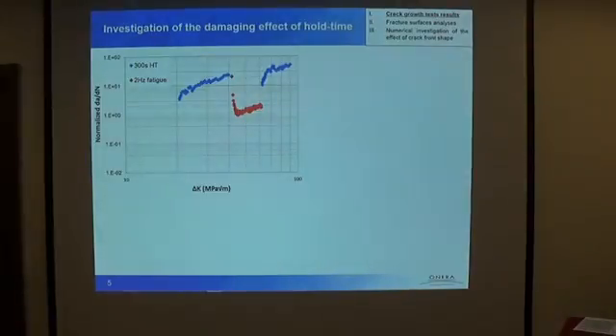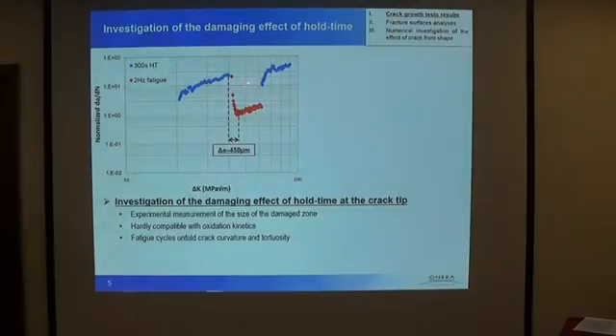In order to investigate the damaging effect of hold-time cycles, we have performed tests that were presented in the literature, consisting in alternating crack propagation under hold-time conditions, then applying a pure fatigue cycle, and then back to the hold-time cycles. What we can see is that at the beginning of the application of the sinusoidal loading cycle, there is a transient with decreasing crack growth rates, and we are able to measure the crack growth extension. Depending on the source, this is believed to be the sign of a damaging effect of the environment that has occurred during the first step, and even it can be related to the size of the so-called damage zone at the crack tip.